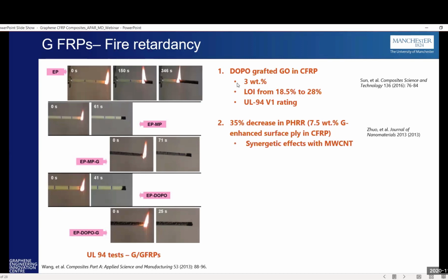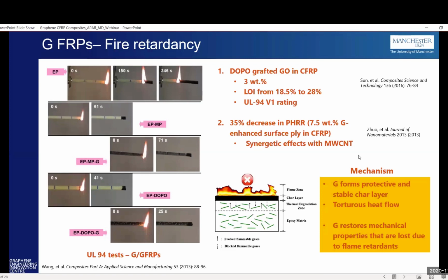And in another study, they managed to chemically graft the DOPO onto the graphene oxide, which was then used to produce the CFRPs. And with just 3% loading, they were able to increase the limiting oxygen index from 18 to 28%. And you don't necessarily have to add graphene to the whole system. In another study, they added graphene only on the surface layer, the surface ply, and still they were able to decrease the heat release rate by 35%.